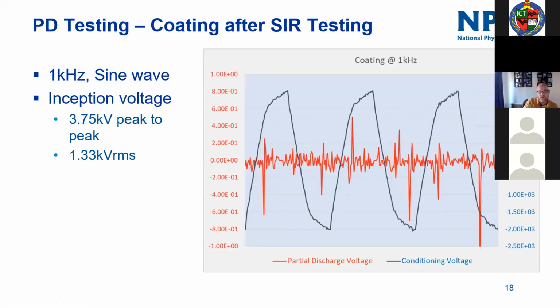This shows a 1 kilohertz sinusoidal wave across the same sample. In this case, it's the inception voltage to start the PD. You can see the PD is a lot more noisy here. It's beginning to occur at different parts of the cycle as well, basically because our amplifier is struggling to drive nearly 4 kilovolts at 1 kilohertz. And we're in the process of upgrading that, hopefully. But anyway, that's talking about 1.3 kilovolt RMS. So that's not far above the 1,000 volt DC systems that we've been playing with now for a couple of years. And you can see lots of partial discharge occurring with this higher frequency system.